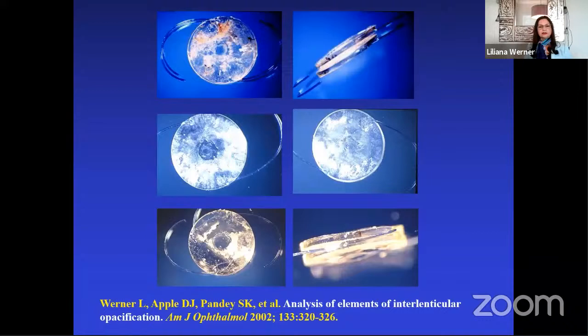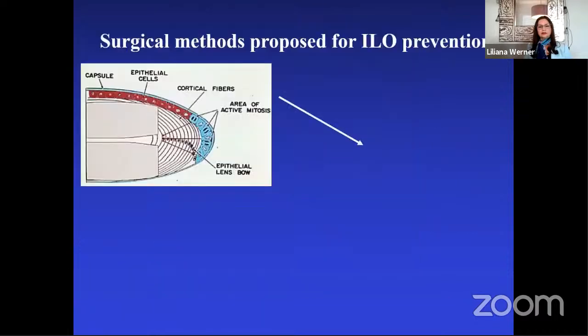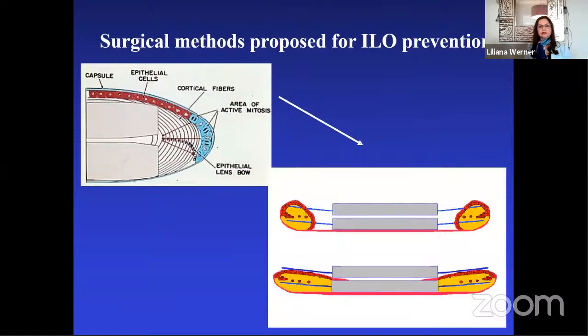Interlenticular opacification is the opacification between two lenses implanted inside of the capsular bag. It is usually observed with 2 hydrophobic acrylic lenses implanted in the bag via capsulorhexis with a diameter that's smaller than the diameter of the lens optic. The AcrySof lens is the one usually affected, as the material of the lens has adhesive properties. The opacification occurs due to proliferation of residual lens epithelial cells within the interlenticular space. The composition of the opacifying material is the same as in posterior capsular opacification.